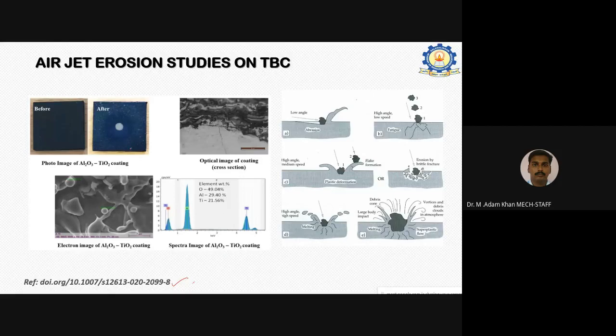This is the base metal in which the alumina titania coating has been done. As it has a self-cleaning property, I have chosen this one: the pure 100% alumina titania coating. Before and after erosion, you can see what is happening during erosion. The hard particles available in the environment will chisel or slide against the object to remove material. To avoid this, we have taken a coating. This is the substrate portion and this is the coating portion. This is after 30 minutes, for a 300 micron A40T coating for 30 minutes at 90 degrees.